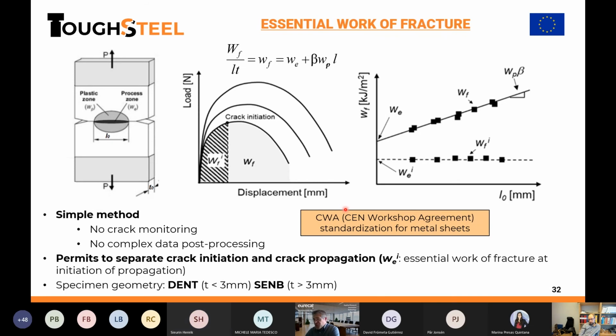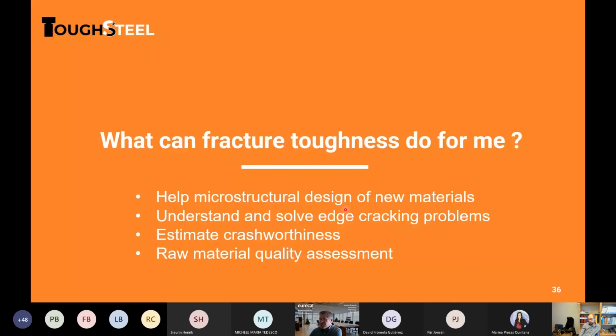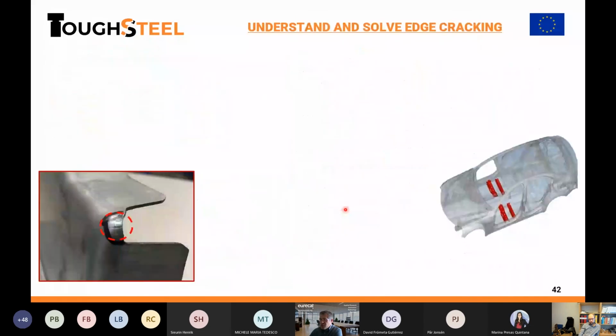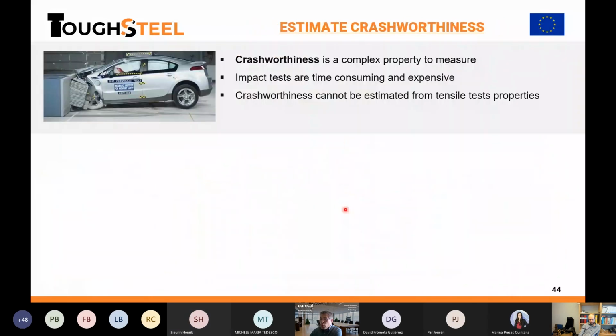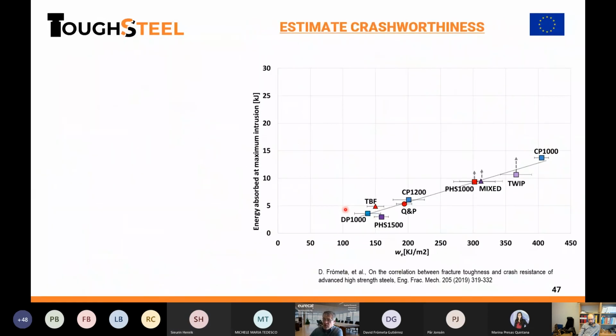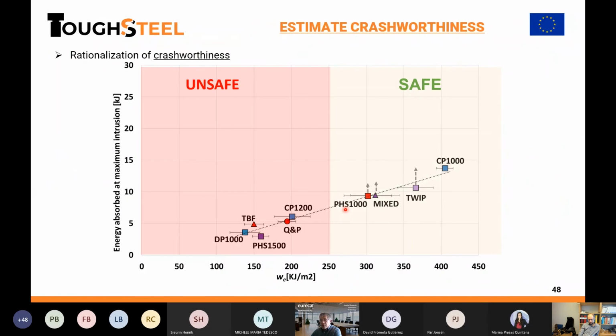Okay. There are some thresholds we saw by expertise. It's about 250. Of course, we should go further. What we are working on now with quite some success, but we don't have time today, is modeling, implementing this in modeling. So that when you form, the way is to allocate at the sheared edges different material properties, a damage behavior, a damage law, specifically for the cut edge. And then we can more or less predict when the crack appears in forming.